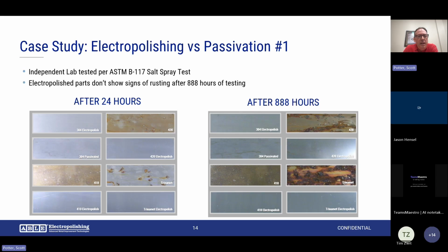Here's a case study. One of our customers shared this with us. They show the exposure of the 420, 410, 304 stainless and Trinimet. You see the exposure after 24 hours, and after 888 hours, the electropolished parts show no rust. But the passivated parts, obviously, the raw parts do show the advent of rust.